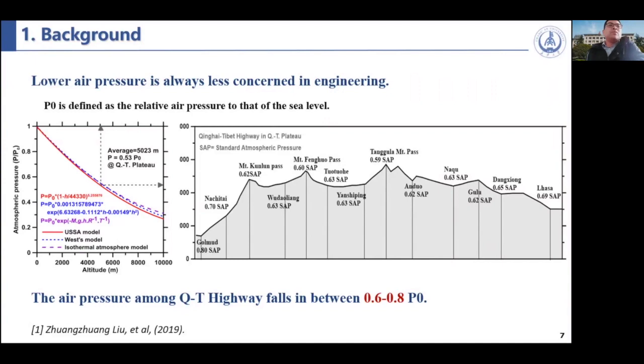For the Qinghai Tibet Plateau, the average altitude is about 5,000 meters, and the related air pressure is about 0.5. Here we define P0 as the air pressure relative to that of sea level. This figure shows the relationship between the air pressure and the Qinghai Tibet Highway. Along the Qinghai Tibet Highway, the air pressure falls between 0.6 and 0.8 P0.